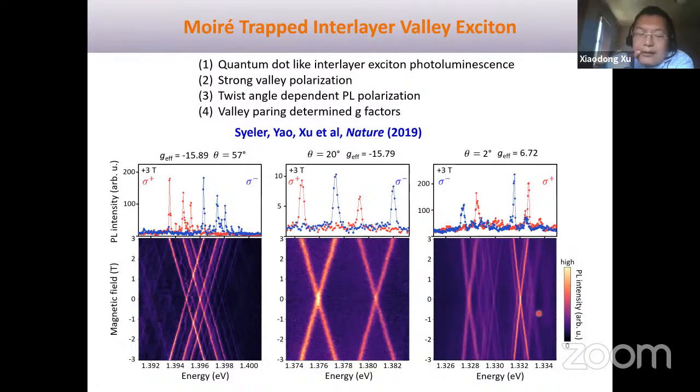That's a good question. We haven't applied a field in-plane ourselves, but another group did apply the magnetic field in-plane. So what happens when you apply it in-plane? Imagine that these electrons and holes are sitting in different opposite valleys, so an in-plane magnetic field doesn't really do much because the spin is pinned out of the plane. What the in-plane field does, for example in the monolayers, is start to create coherent states between two different valleys, kind of rotating them. But it doesn't really change the g-factors. The g-factor is pretty much determined by the spin in the out-of-plane direction. Yeah, that's pretty interesting.